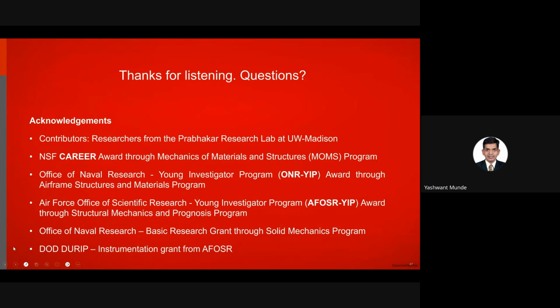What are the research facilities required for maintaining uniform particle size? It's a V-shape hopper mixer that we got, and that was used to mix. But to characterize, we used SEM to basically visually confirm that it was uniform. You could also potentially do microscopy by polishing and looking at the surface at different cuts. You could also do micro CT scans at very high resolution to measure the same. CT scan would be non-destructive, so you could use micro CT scanning as well.